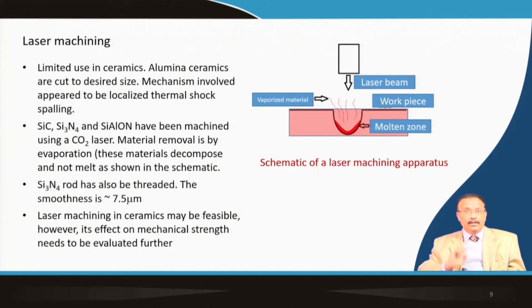As you know, this material will decompose and not melt, as shown in this view graph. So, it will just decompose. Silicon nitride rods are threaded, but the smoothness is quite good, about 7.5 micron, by using this laser machining. Laser machining in ceramics may be feasible, but its effect on the mechanical strength is not very well known at this stage, because not many different types of ceramics have been used for laser machining to test their effect on mechanical property. But this is one of the ways to machine the sintered ceramic part.